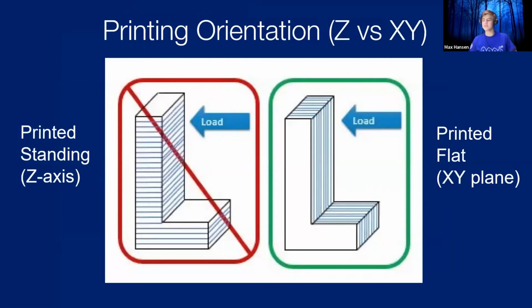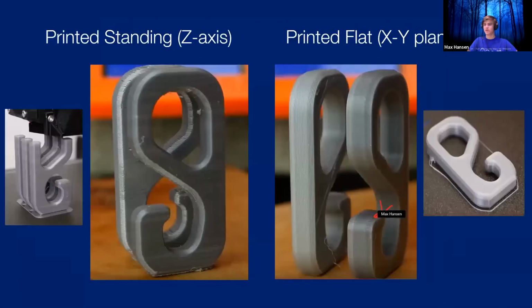And then probably the most important thing to keep in mind when looking at printing, and we'll see through his tests, is the print orientation. So you can print on the z-axis, as in this left-hand picture here, where each layer is on top of the other, and it just prints straight up as your part goes on. And this, as we will see, is fairly bad. And then on the right, you can see we have a printed flat, where it's printed on the XY plane, and it's printed from this bottom layer upwards. And that ends up being much stronger.